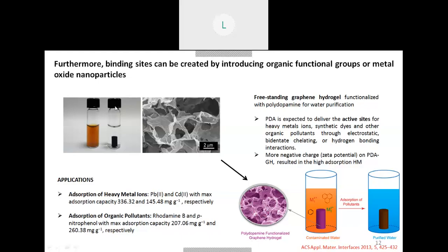And this was, when characterized, found to be highly porous. And you don't need to go for any hydrothermal route or anything. You just need to put these two candidates together, and you will find such a material. And when you incubate this material with pollutants like benzene or heavy metals or dyes, a huge adsorption capacity can be achieved. So these were some advancements in nanotechnology, which enabled you to jump from carbon nanotubes to graphene to this PDA-functionalized hydrogel.